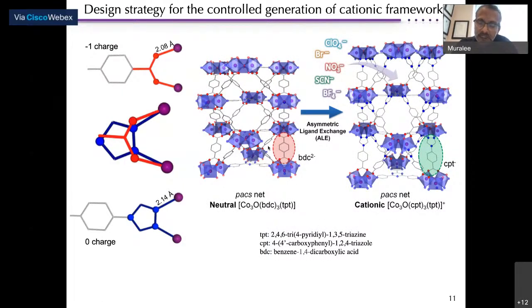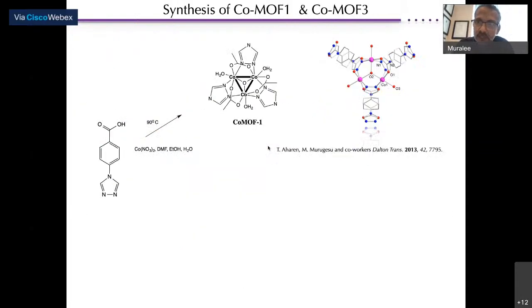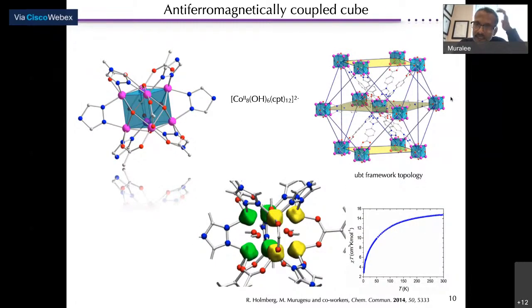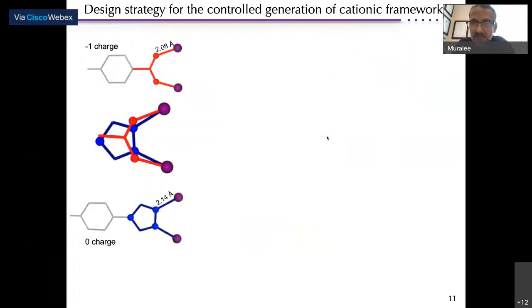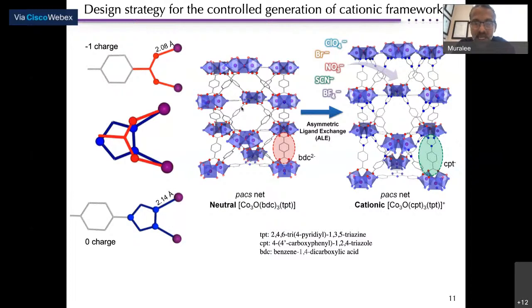So here is this framework that initially you saw with the cobalt, if I may go back, this framework, and I mentioned this is unstable. But if you take a TPT ligand and stabilize this framework, here the TPT ligand acts as pillars, but also holds together and forms this framework with a pack net using this benzene dicarboxylic acid. But if you change it to CPT, this asymmetrical linker, now you are retaining the packnet, but the charge is changing. It becomes a cationic framework, which means we should be able to do anion exchange systematically, put some anions and exchange with it. And this is the ideal scenario for us.